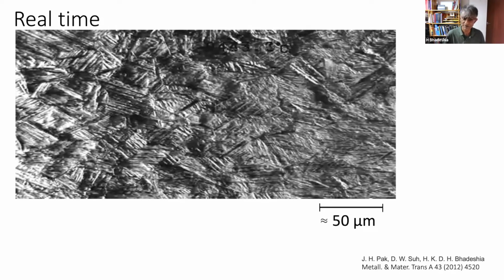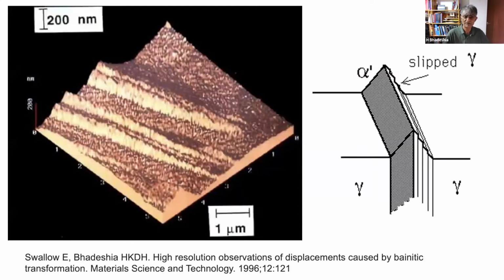So you can think about them like slip. There is a particular system on which these plates form, a crystallographic system, and the displacements are in a particular direction, but there's a phase transformation at the same time. Now, I explained to you that this is too coarse a scale to observe what's going on, but if you use an atomic force microscope, then you have the resolution to look at individual platelets, and this is a similar experiment done using atomic force microscopy, and you can see the large shear deformation associated with each of the plates.